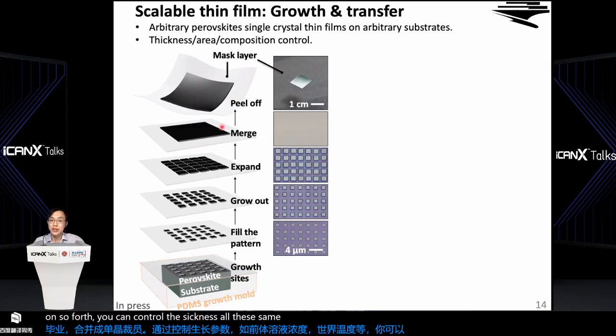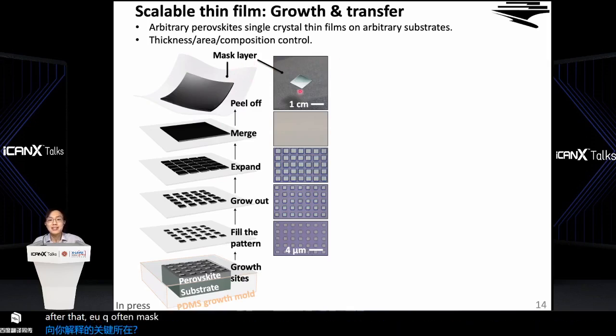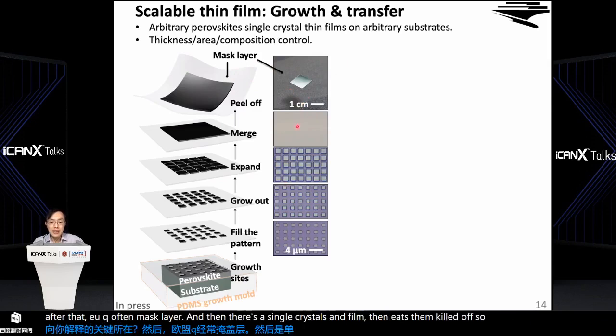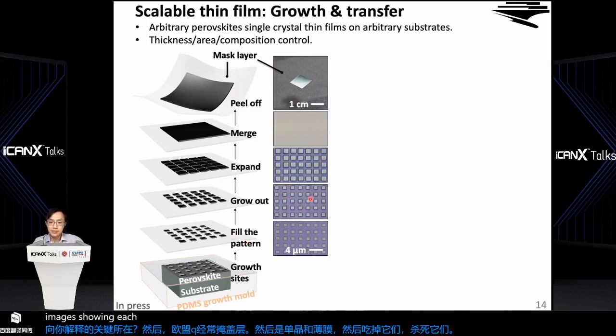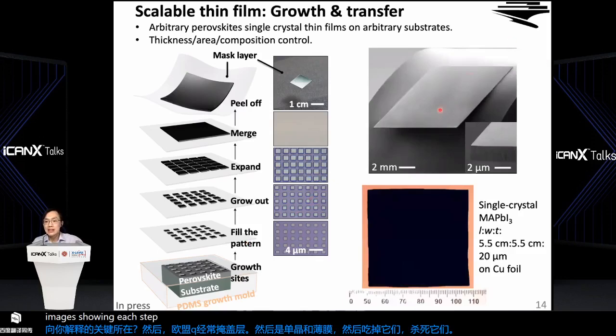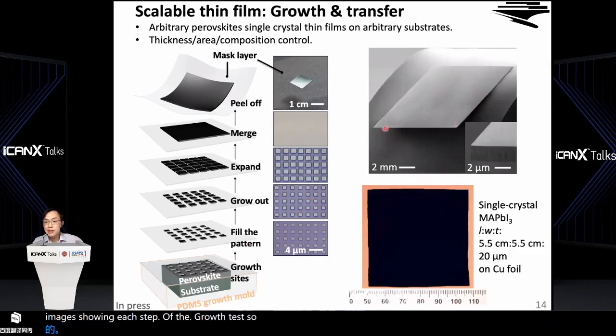And this is very critical. I'm going to explain to you later. And then after that, you peel off the mask layer, and then the single crystal thin film is peeled off. So on the right here are a series of images showing each step of this growth process. So what you're looking at here are some images showing this thin film of 1 centimeter by 1 centimeter with a thickness of around 2 micron, and the thinnest we can grow is about 600 nanometer in